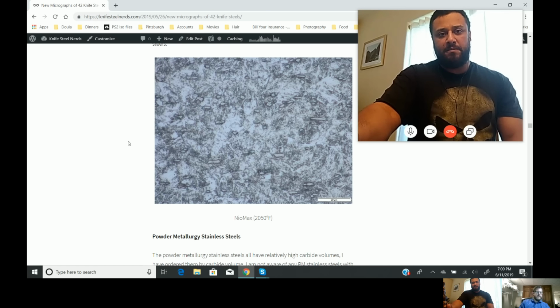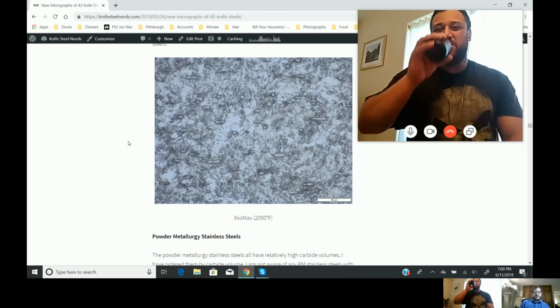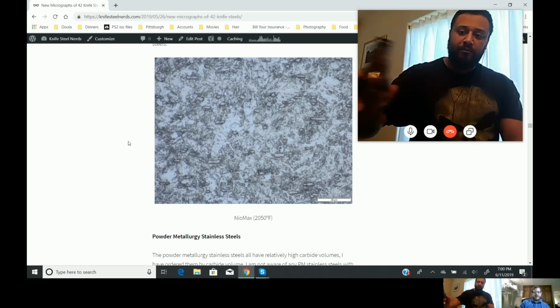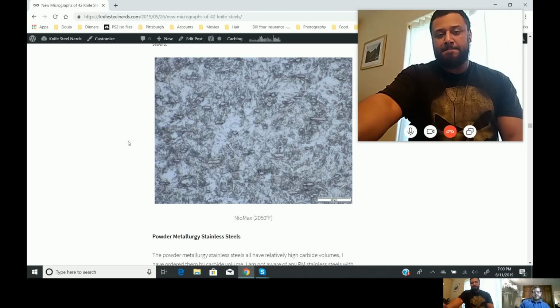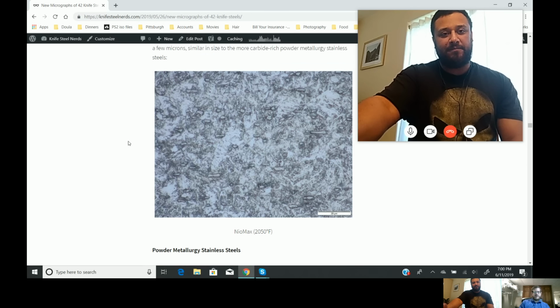Yeah, exactly. The steel was designed to be produced without powder metallurgy with as fine a microstructure as possible. And powder metallurgy is still going to be finer in this case with the niobium carbides, but it looks like we didn't need it. The toughness came out as good as AEB-L, which is a very tough stainless steel. So pretty happy with the results so far.